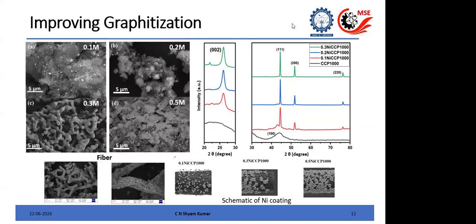Now, when it comes to engineering a carbon material, to tune the properties, you need to have a very good understanding of the microstructural evolution, how the microstructure is changing, how the internal structure is changing. And most of the characterization that we do is post-mortem characterization. So you take your sample, you heat it to 1000, take out your sample, and look at it in Raman or in SEM or in a TEM.